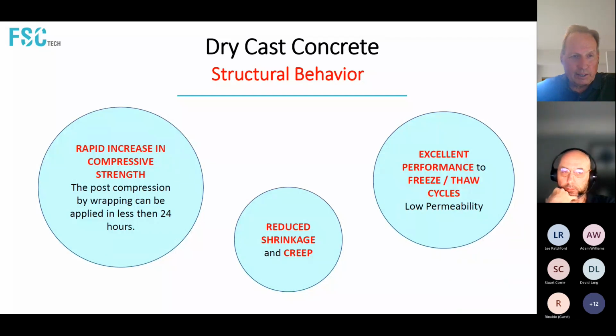The structural behavior of dry cast, because you've got such a low water cement ratio, you have a rapid increase in compressive strength, and it'll allow you to handle the product and have enough compressive strength within 24 hours that you can perform the wrapping operation. Again, we have reduced shrinkage and creep, and of course the dry cast has very excellent performance to the freeze thaw cycles.